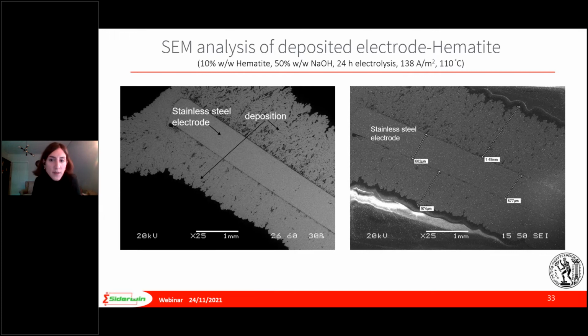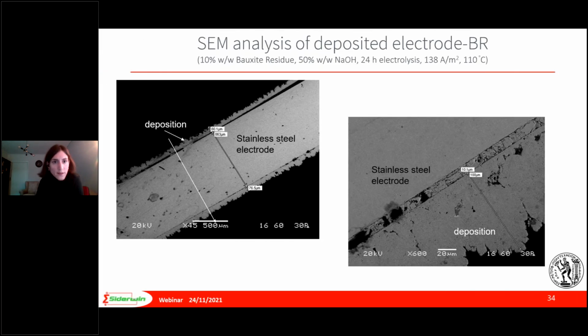These are some images from the scanning electron microscope showing the deposition from pure hematite from experiments that were run at 138 ampere per square meter. The metallic iron deposition seems to be thick and tightly connected to the electrode surface. To compare the two raw materials, the bauxite residue's deposition was also studied with the scanning electron microscope, and unlike the hematite deposition, the bauxite residue's metallic iron is not as strongly connected with the electrode surface. The right image shows that there are a lot of gaps between the deposition and the stainless steel cathode.